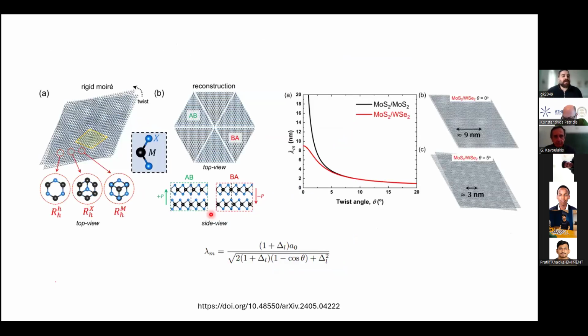So in these heterostructure bilayers, we can have either a rigid moiré superlattice with a larger unit cell that you can see here, or another thing can happen: for very small twist angles, you can have atomic reconstruction. So basically, with very small twist angles, the lattice will try to shift back a little bit to minimize the energy of the misalignment. And this actually creates ferroelectricity. You can have domains where you have out-of-plane polarization. We can see here that the moiré periodicity depends strongly on the lattice mismatch and the twist angle.